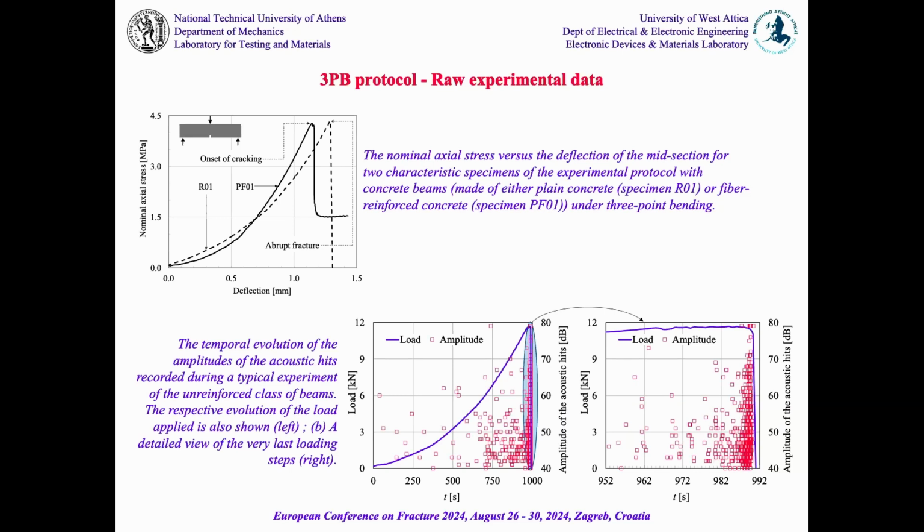And you can see here also some data about the mechanical response, the load and the amplitude of the acoustic events, and a magnified view at the very last seconds. It is clear that the vast majority of events and sources appear at the very last second of the experiment, either it is plain or it is reinforced.